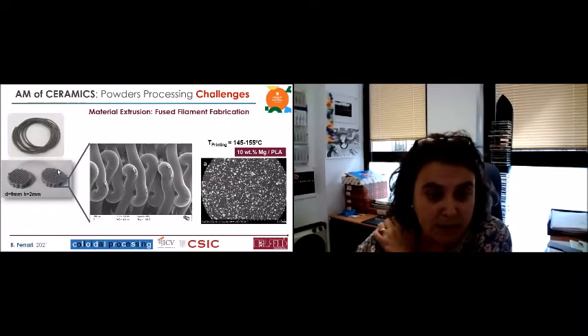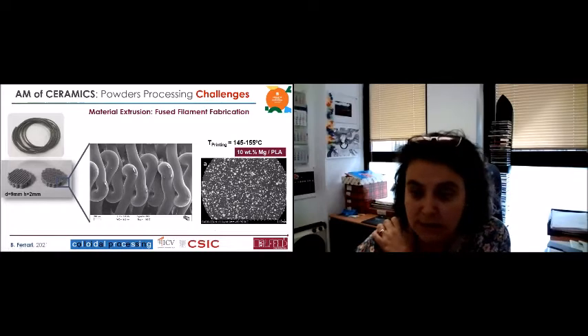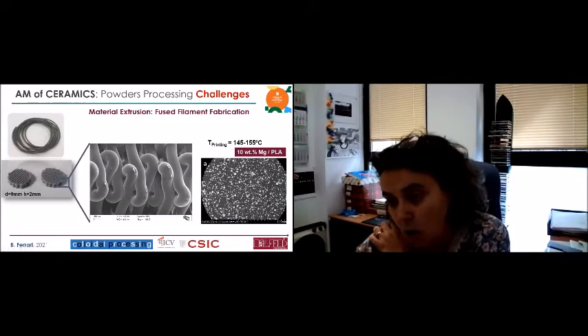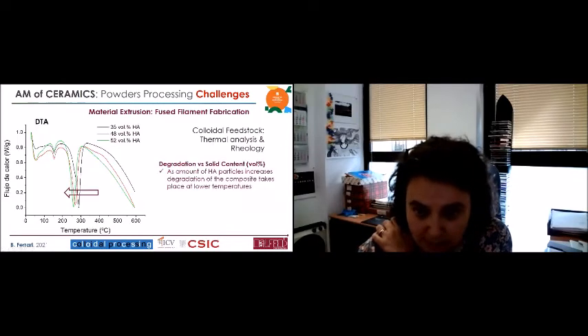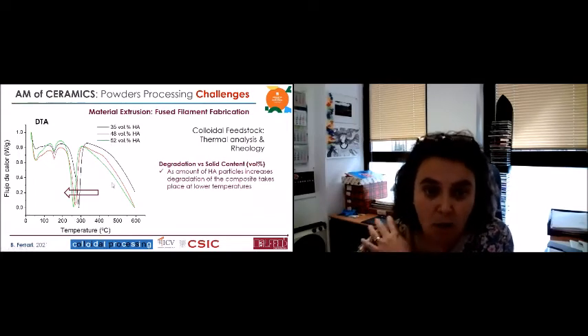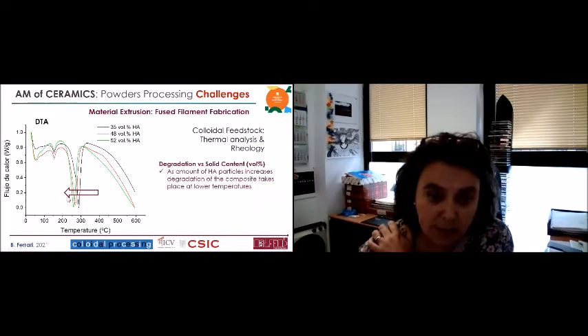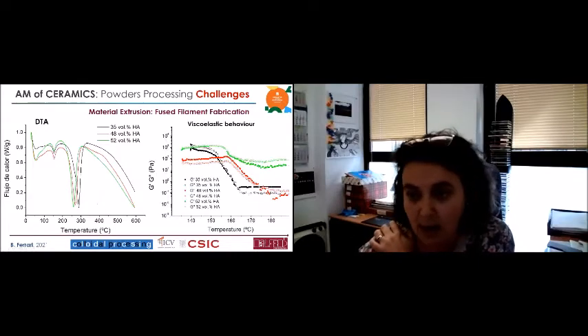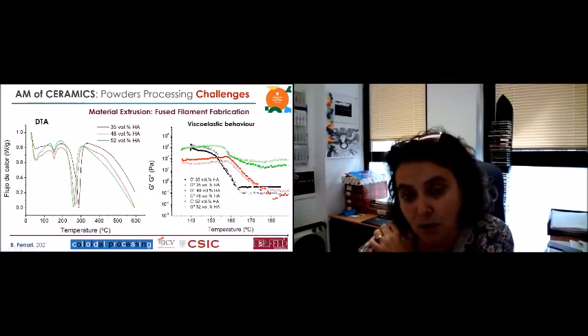And this is the filament. These are our 3D parts, some scaffolds. You can see here how we print, and how the particles are isolated and mixed with the thermoplastic. We need to take care of the thermal characteristics of our filaments, because as we increase the amount of particles in the filament, in this case also hydroxyapatite, we are decreasing the degradation temperature. So the filament is degrading faster, right? And we also need to take care of the viscoelastic behavior of the melt polymer with the particles inside. It's very important.